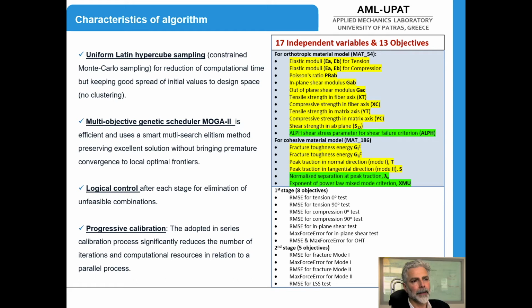Normalized separation at peak traction, λ naught, deals with the actual shape of the traction separation law, and the exponent deals with the mixed mode criterion. In the first stage, the objectives for the optimization were the RMS values for the curves and the RMS for the maximum force error in plane shear, while in the second stage of the optimization scheme, the five objective functions were the curves in mode 1, mode 2, the RMS for the maximum load and the RMS for the ILSS test.